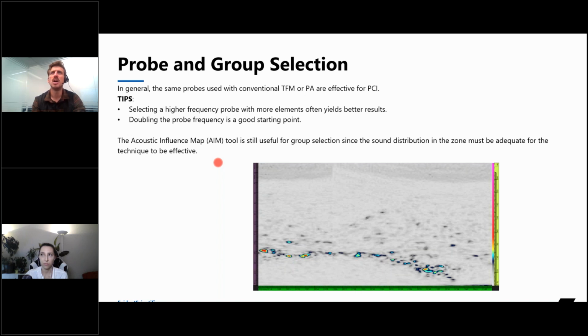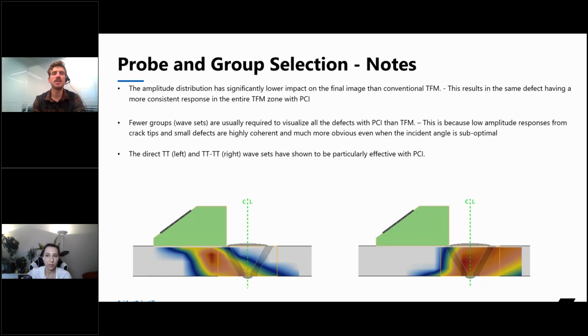But also the acoustic influence map or AIM that we have on board the OmniScan is still a very useful tool when selecting groups, because the sound distribution of the part must be adequate in order for the technique to be effective. So discussing the AIM, like Emily was mentioning, we're less sensitive to the distribution in the part because we're able to pick up on much lower amplitude signals, but we still need to have sound that comes into each area of interest. So here I have a TT group with an angle beam. This is from an A32.